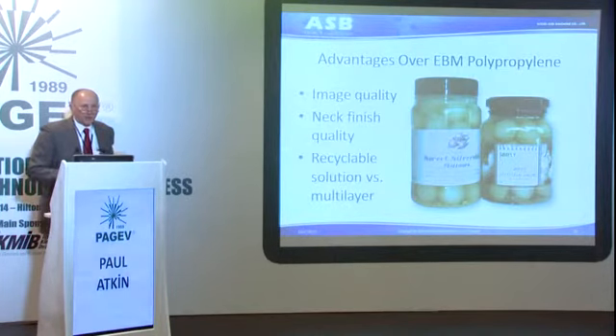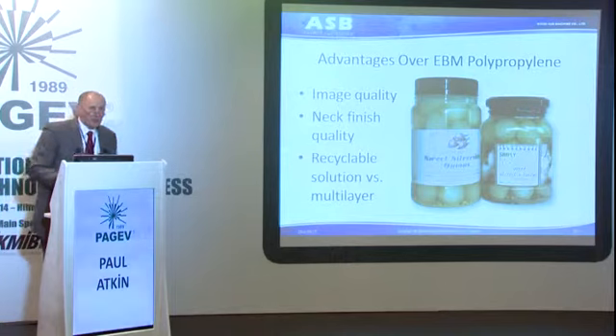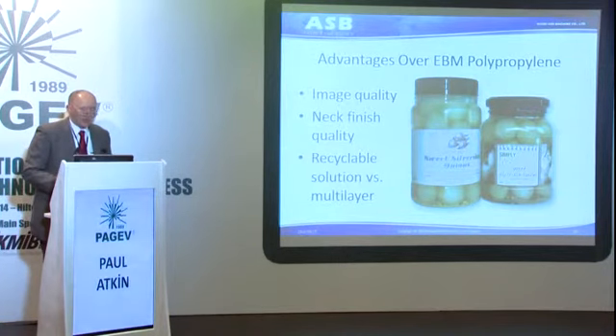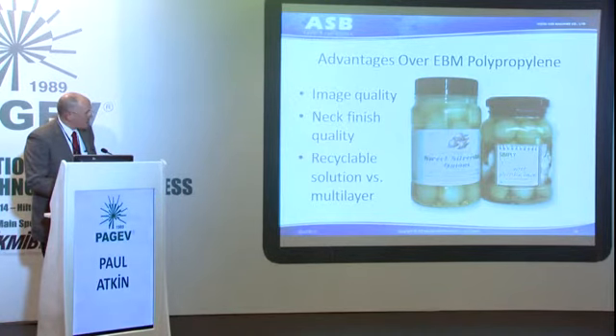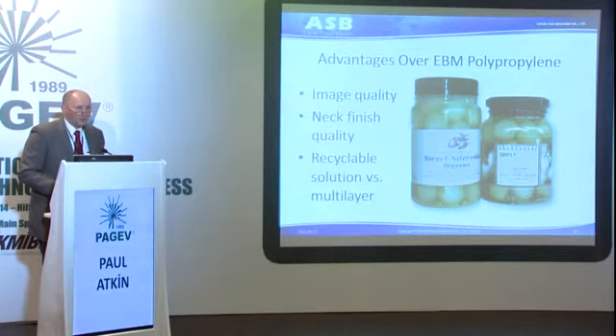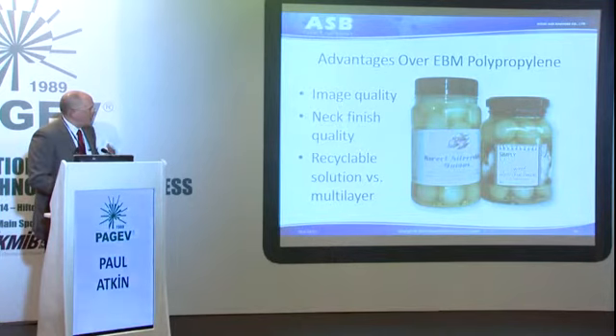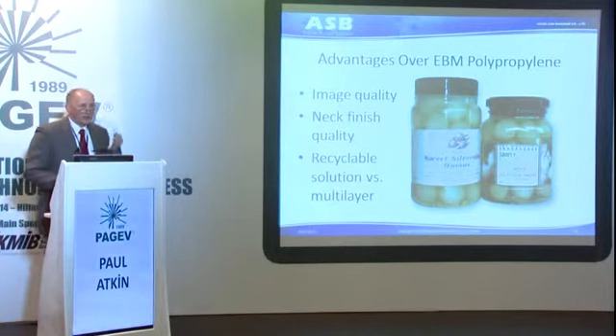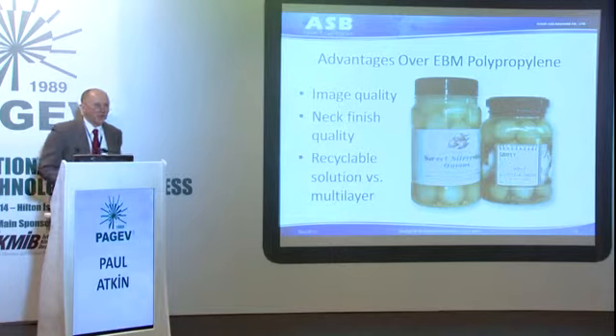But sometimes people are not just changing from glass to PET, they're changing from other plastics into PET. And this is one example which we did. This is actually pickled onions, which previously were in an extrusion blow molded polypropylene multi-layer container. And the image quality improvement is dramatic to see, but also because it's not multi-layer, we've got improved recyclability of the finished container, which I think will make some of our members of the ministry happy, I hope.